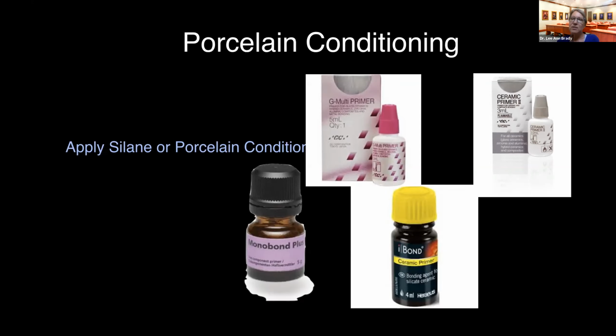Now, if you're seeing discoloration and you're seeing it quickly, that's not the amines. That's probably more than anything a hemostatic agent. So if you're using a liquid hemostatic agent, it can react with bacteria in the dentinal tubules and turn the whole prep dark, and then everything looks dark. That'll happen in weeks to months. The actual color shifting of the resin isn't a week to month phenomenon, it's a year phenomenon. So if you're getting something quick, that's not the chemistry of the dual cure, that's something else in your process.